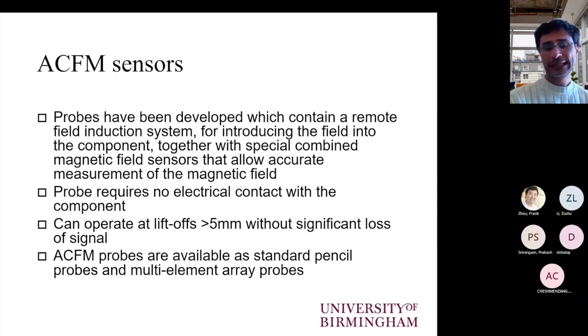inspection quality overall. The ACFM does not require electrical contact, in the same way that eddy current testing and magnetic flux leakage do not require electrical contact. And they can also operate at higher liftoff than eddy current testing. So typically, liftoffs up to 5 millimeters are possible, especially if we are trying to detect larger defects. If it's smaller defects, of course, we need to try to be as close as possible. Eddy current testing, however, above 2 millimeters, the signal becomes very low. So it is not a very good idea to try and increase the liftoff beyond that. And ideally, you should keep it even below 1 millimeter if feasible.